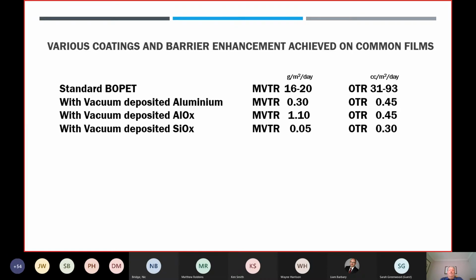So you put some aluminium, traditional vacuum deposited aluminium, onto the film, and you lower the MVTR to 0.3 and the OTR to 0.45. You can put an AlOx on, which is clear and is used extensively in retort packaging for reheating in the microwave, and you see the improvement that you get. And then with vacuum deposited SiOx, you get an incredibly big improvement, and the best on the chart there for addition of that. But it is very expensive, and it also has to be top coated to prevent damage to it, as is normally the case with AlOx.